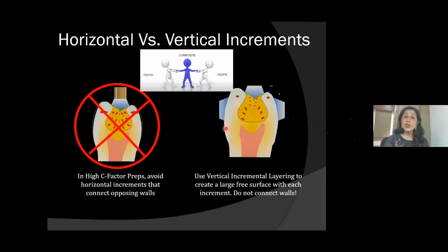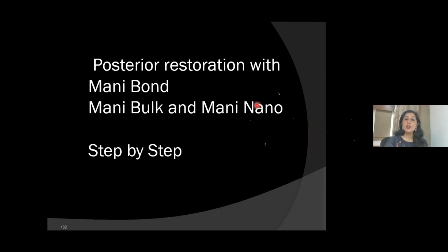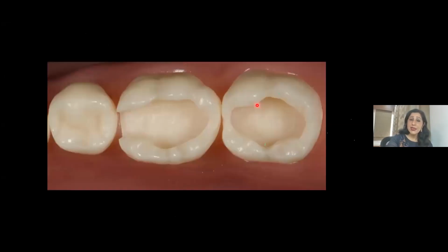So using vertical incremental layering, you create a large free surface area with each increment because you have not connected the walls. So every increment has a large free surface area to release its stress. And then you put another increment. This also has a large free surface area to release stress. So this is how you incrementally build your tooth with vertical increments. I'm going to show you a case of a posterior restoration with Mani Bond, Mani Bulk, and Mani Nano. Let's see it step by step.